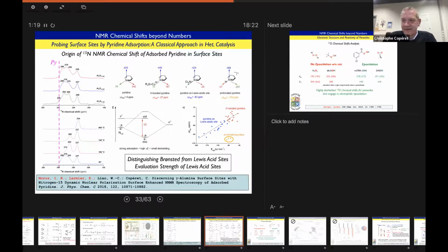So in some cases, you learn the same thing, but we are currently writing a paper where, in carbon NMR, the chemical shift window is still rather small, even in alkylidene, the chemical shift window is 2000. Right now, we are writing a paper on molybdenum NMR. And in that case, the chemical shift window is 3000 ppm. So then you can actually pick up subtleties that do not appear in the carbon-13 NMR. So I think it's complementary.